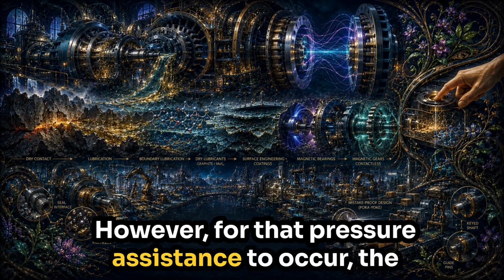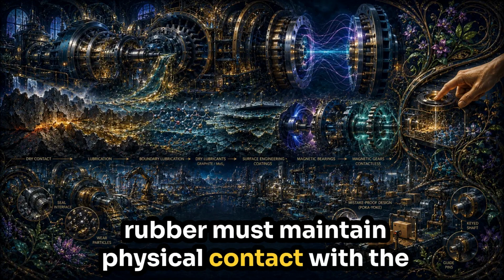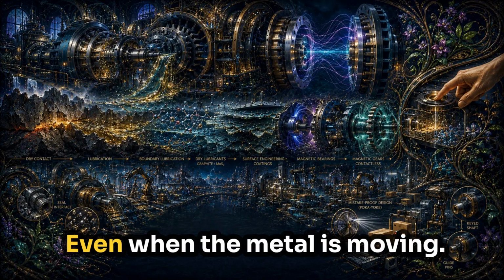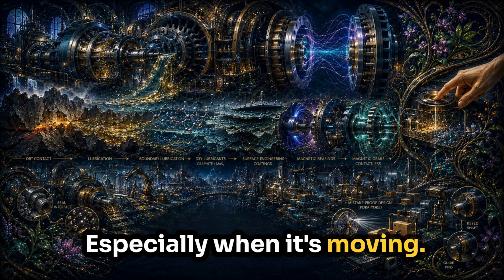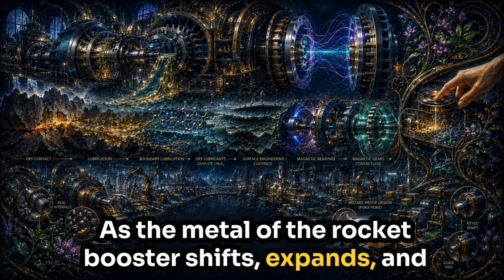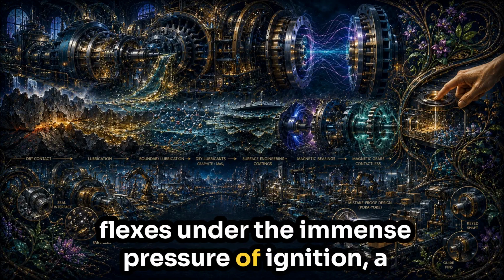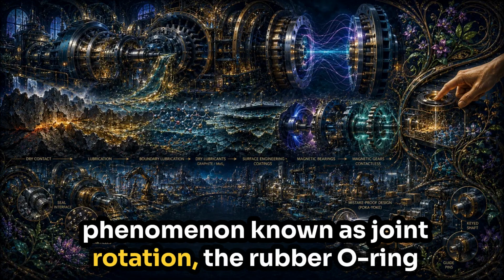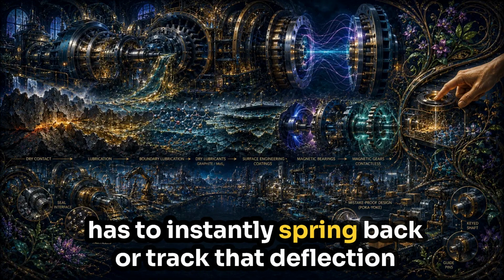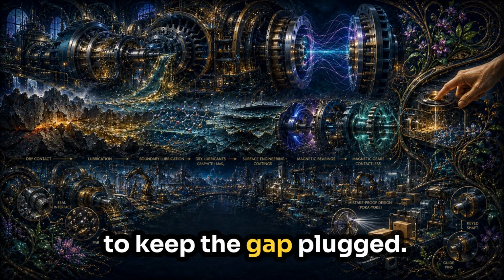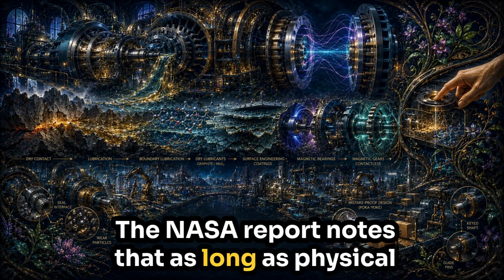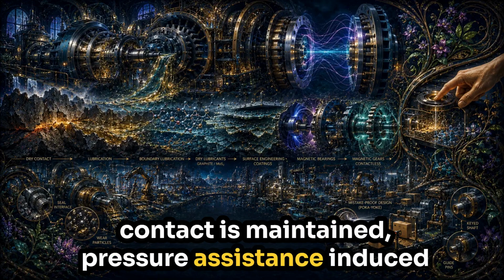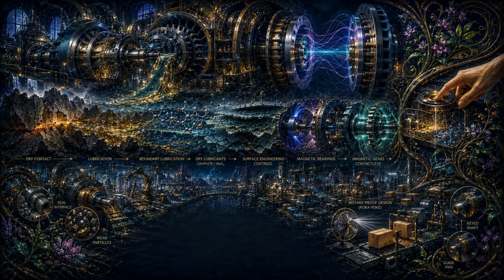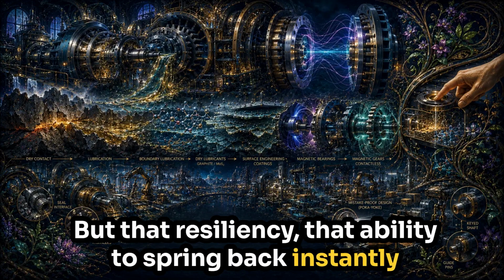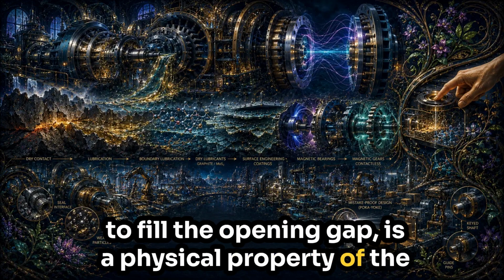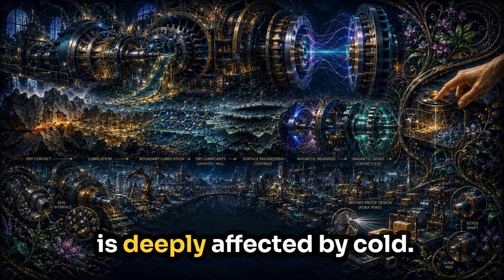However, for that pressure assistance to occur, the rubber must maintain physical contact with the sealing surface at all times. Even when the metal is moving? Especially when it's moving. As the metal of the rocket booster shifts, expands, and flexes under the immense pressure of ignition, a phenomenon known as joint rotation, the rubber O-ring has to instantly spring back or track that deflection to keep the gap plugged. The NASA report notes that as long as physical contact is maintained, pressure assistance induced instantaneous sealing. But that resiliency, that ability to spring back instantly to fill the opening gap, is a physical property of the polymer chains within the rubber, and rubber chemistry is deeply affected by cold.